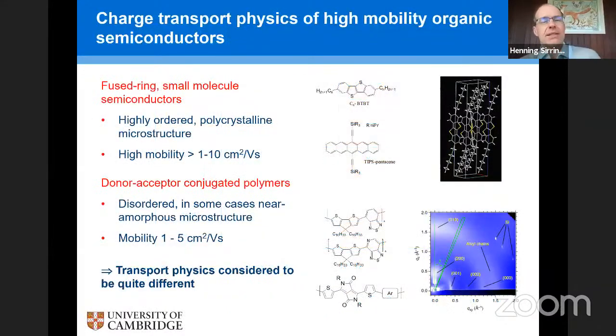So much for applications. As I said, it's a physics talk, so I don't really want to go much further there. I now want to talk a little bit about the different types of organic semiconductors, and there's essentially two different material systems. There are what we call small molecule semiconductors, and you can see some examples of that on the top of this diagram here. It's essentially small conjugated units where you have these fused benzene-like rings. Sometimes you have flexible side chains attached to the periphery, and that helps to induce the solution processability of these materials. But these small molecule systems are typically highly ordered polycrystalline materials. You can grow single crystals and achieve fairly high carrier mobilities, as I said, on the order of 10 centimeters squared per volt second.